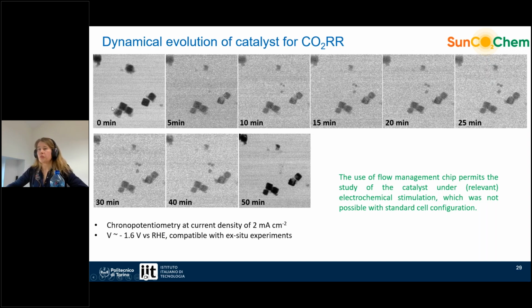And we observed that some of the cubes, as this one, for example, remain more or less unchanged during this very long experiment. Some disappear, so dissolve quite much during these experiments, and some undergo some changes, so it's not completely disappeared, but it's not remaining unaffected. But the very important message from this is that the use of this flow management chip permits us to study the catalyst under relevant electrochemical stimulation, which was not possible with the standard configuration.